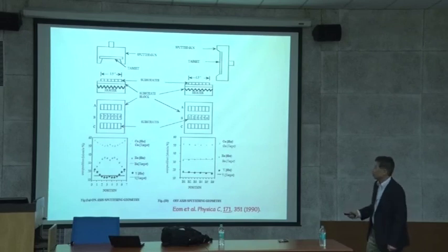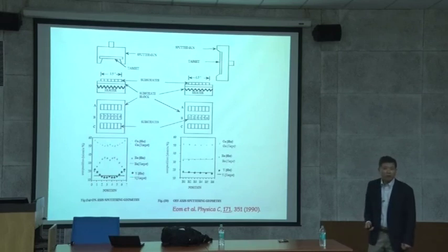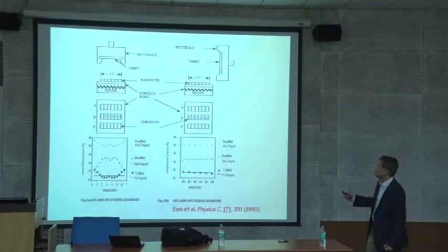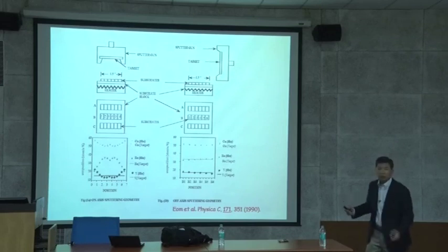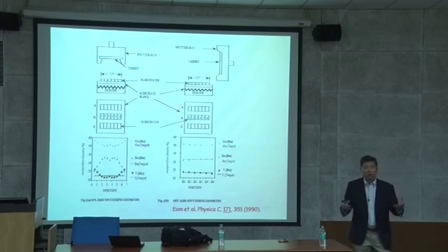And not only non-uniformity, it still accumulates a lot of off-composition. So that's why it's a lot of struggle. But just by changing the geometry, your composition is pretty uniform over the area, like a 2-inch area. The thickness and composition are very uniform, and the properties are very, very uniform.